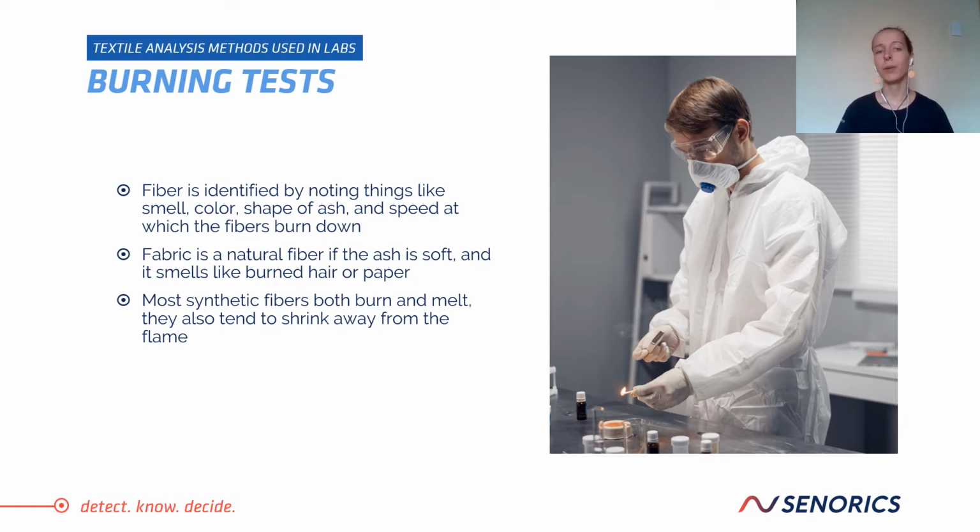Most synthetic fibers burn and melt. They also tend to shrink away from the flame. Synthetics burn with an acrid chemical or vinegary smell, and they leave a plastic bead. Nylon smells slightly sweet when burnt, and polyester smells like vinegar.